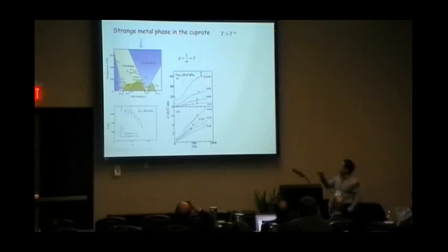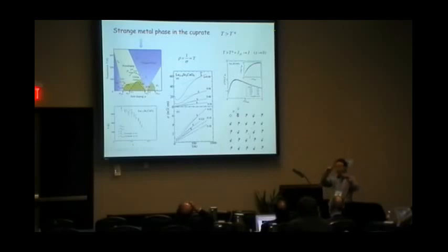Another characteristic of the strange metal is the spin. There's still a lot of spin at no doping, okay? But at such a high temperature, as mentioned, all the orders are melted away, including the short-range antiferromagnetic ordering. So in other words, the spin-spin correlation length will shrink to within one lattice constant, such that the uniform susceptibility decreases with temperature, smoothly connecting to the classical limit of the Curie case. Actually, this peak represents the T-star here, and these different dopings scale together. It looks like they are fit very well by the Heisenberg model, except that J is replaced by J effective, which has strong doping dependence. So this is a strange metal: the spin degrees of freedom are all summarized, and the charge will do the linear T. So what's the underlying physics related to it?